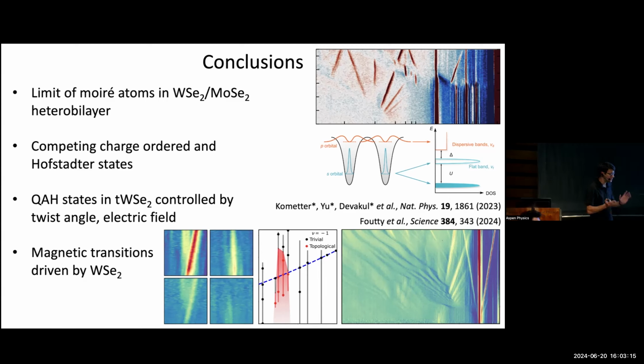There's even one experiment that I heard about at the March meeting, which is the big yearly condensed matter meeting from APS, from Pablo Jarillo-Herrero's group, where they actually took three magic angle twisted trilayer graphene samples, separated them by boron nitride, put them on top of one another, and looked at superconducting transport in various different configurations. So it's really, really hard, and in a few select examples people have done it, and it is a really interesting direction to push.